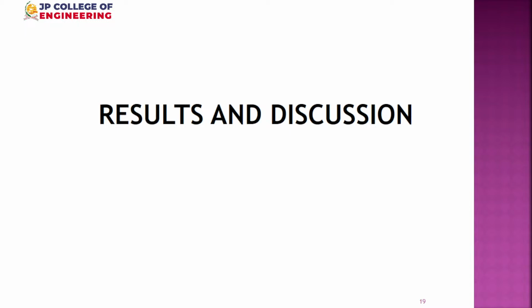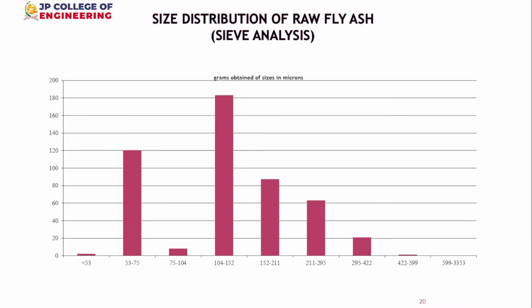Yeah, next slide, to go for results and discussion. So this is the raw fly ash. If you see the center line, which has a larger percentage in the bottom, this is around 100 micron, this size in micron versus percentage. So the ash received has a mean value of around 100 micron,